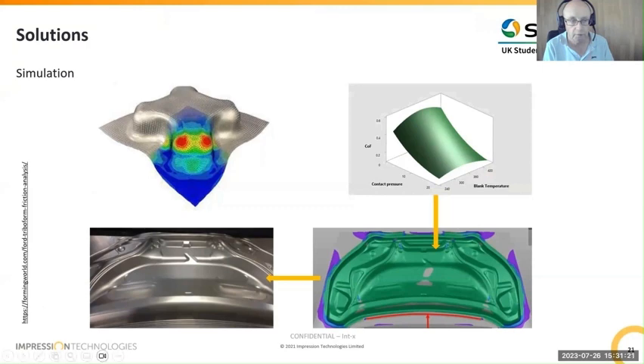A graph of which you can see on the top right, and apply that to an actual production part. And again, we can predict more accurately with this data where the thinning is going to occur, where splits might occur, where we need to apply lubricant, where we don't need to apply lubricant in some cases too, which can be just as important. Reducing the friction where you need metal flow is one thing. Increasing the friction where you don't want it to flow is often just as important. And if needs be, we go back to the OEMs or whoever we're dealing with, discuss what certain issues we're having, and sometimes they will agree to a slight design change, so that the part can be more easily made.